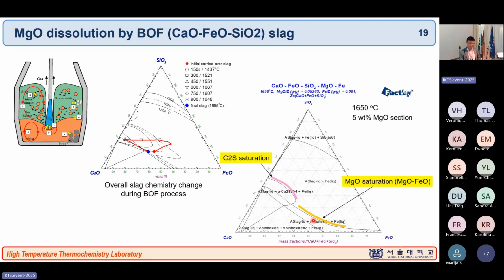And then if you look at what the MgO saturation line is here, it is this line. And this is not strictly an MgO saturation line because in this CaO-FeO-SiO2 slag, MgO and FeO make a full solid solution. So this is the MgO and FeO solid solution. So typically when you examine your MgO refractory after BOF operation, if you take it out, on the interface side you can see a lot of FeO dissolved in the MgO refractory, because it makes a solid solution.